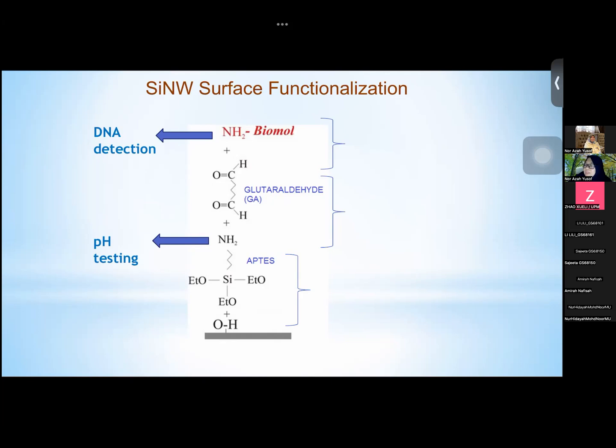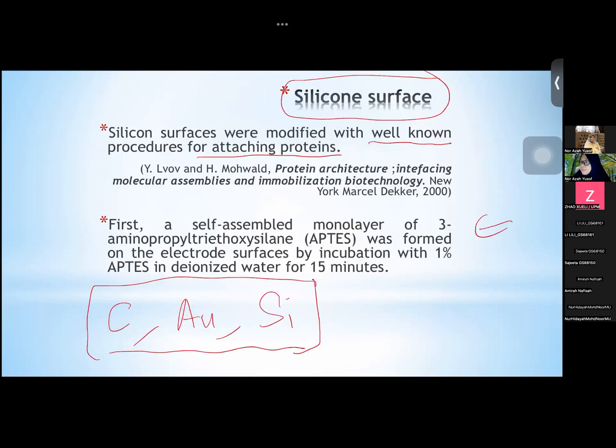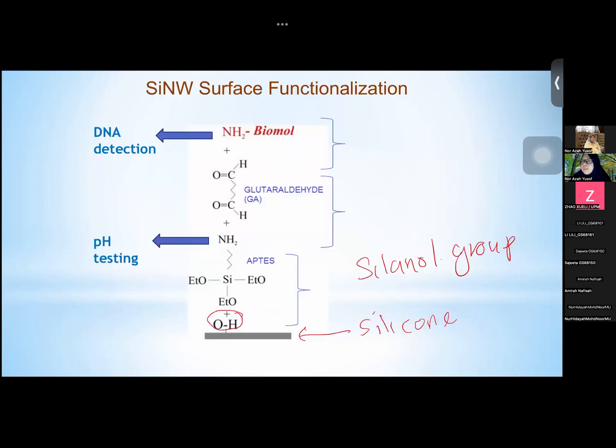All right, you start with this, silicon. Okay. In order to get this silanol group, the alcohol group, okay, this is the protocol. So you just incubate in, sorry, sodium hydroxide. Then you will get this silanol group. So the next one is to get the amine group. Okay, this is one of the steps that you can do. Okay, because once you have amine group, you can choose. You can use the amide chemistry.